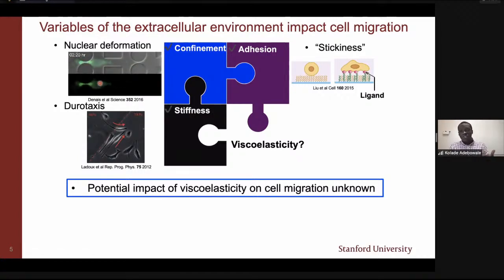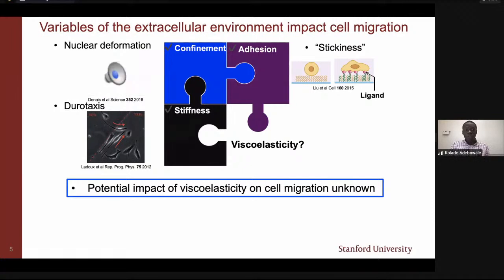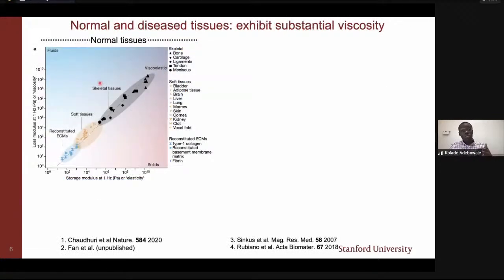But why is viscoelasticity important? It turns out that normal tissues are viscoelastic, and this was summarized by a recent review article that was published with important contributions from some of the faculty at Penn. This data is plotting the loss modulus or the viscosity in the material on the y-axis as a function of the storage modulus. And if you look along the diagonal line on this plot, you can see that there are a lot of data points clustered around this diagonal line.